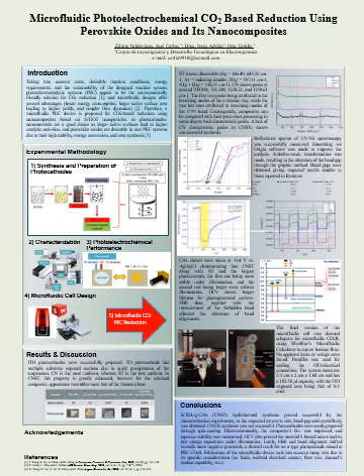However, a second composite was also obtained through the same process, with the only difference that it was lastly calcined at 520 degrees Celsius in order to compare possible improved crystallinity. As for some materials, with calcination comes enhancement of crystallinity.